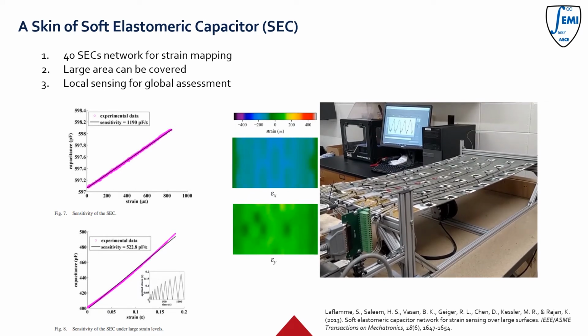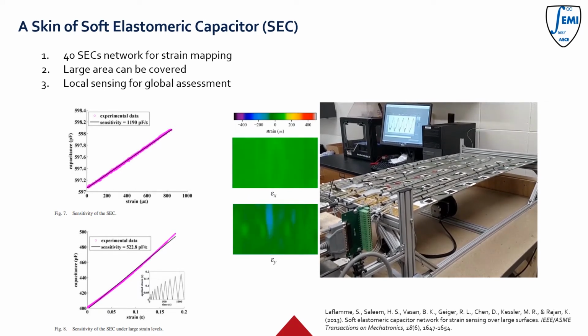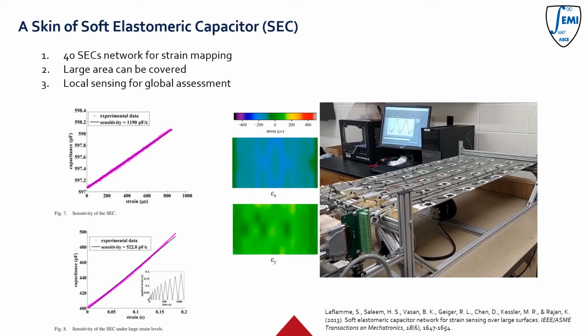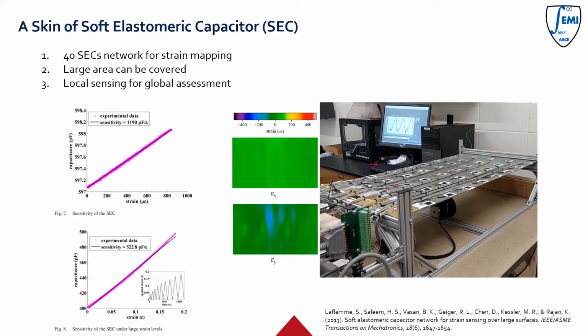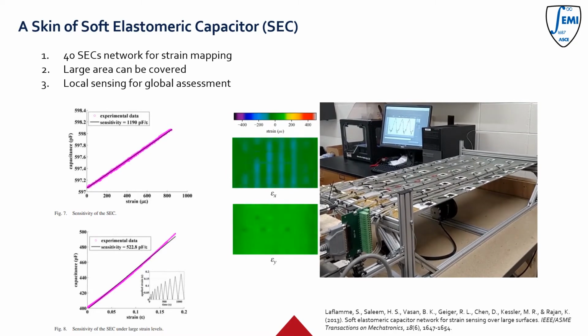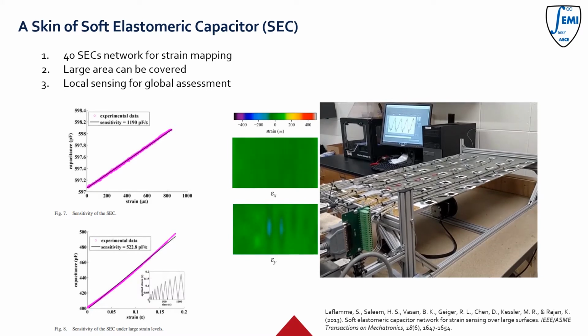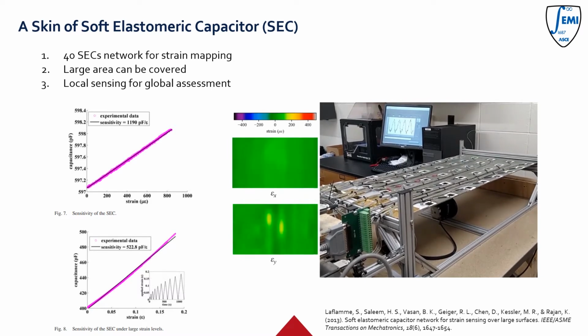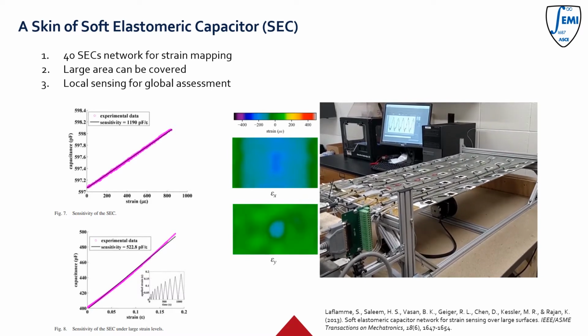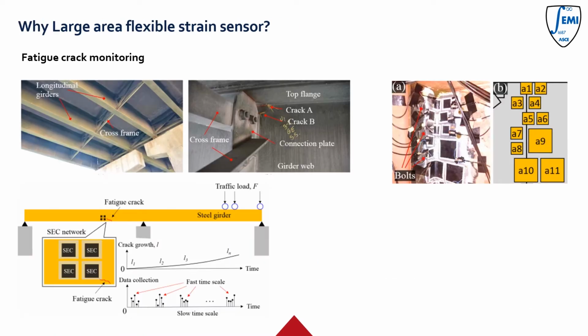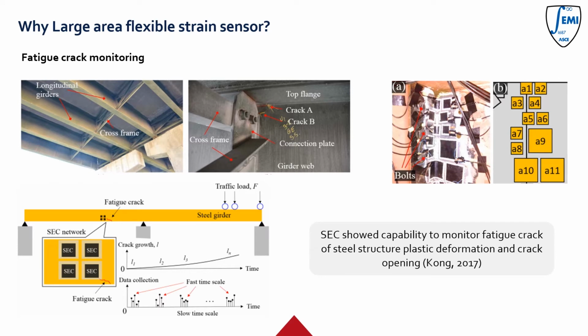The right video clip shows a large area deployment of 40 SECs on a fiberglass plate. Both directional strains along the x and y axes were able to be characterized. The SEC showed a global strain field assessment capability with excellent coverage and resolution. The SEC was also employed for fatigue crack monitoring on a steel bridge under traffic load. The SEC arrangement showed great capability to monitor distortion-induced fatigue cracks.